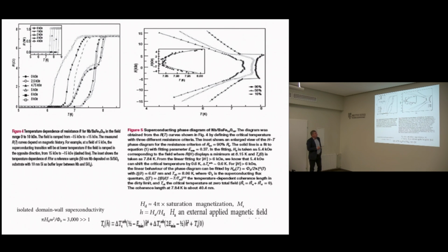However, if we apply some magnetic field, namely close to saturation, saturation is around 5.4 kOe, we see that Tc is higher than Tc in zero magnetic field.